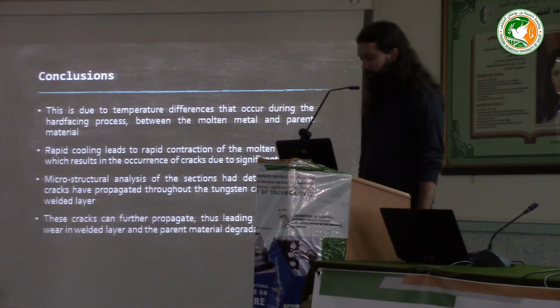The microstructural analysis of the sections determined, as I mentioned, that the cracks propagated mostly through tungsten carbides, which explains why there are significantly more cracks in the areas with higher tungsten carbide concentration, but did not, once again, propagate through the parent material. However, as we have seen, these cracks can also further propagate, which can lead to significant wear due to fragmentation and the further degradation of the parent material.